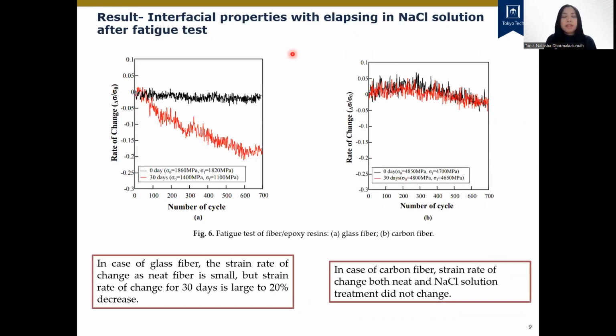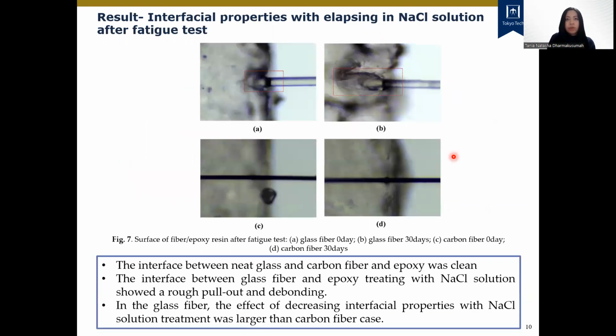And besides tensile strength, we also conducted interfacial property tests after immersion in an NaCl solution, following a fatigue test. This is the neat fiber before immersion in NaCl, and the red one is after NaCl treatment. We can know that in the case of glass fiber, the rate of change is decreasing, but meanwhile carbon fiber does not change. Okay, the strain rate did not change.